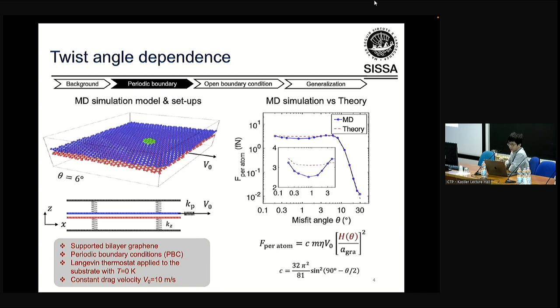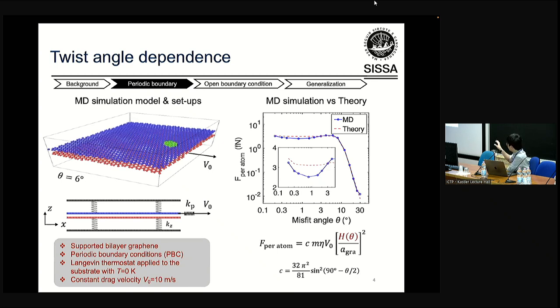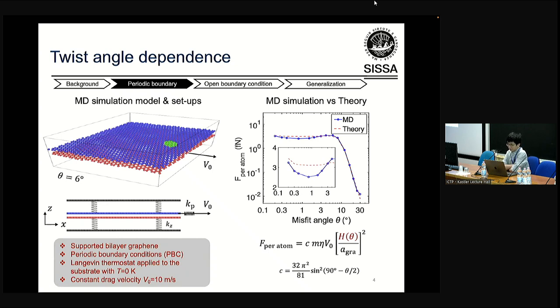Here is the simulation model. We drag the upper layer while the lower layer is stationary, and we highlight the central green region. In the right figure, the blue dots show friction per atom as a function of the twist angle (misfit angle). You can see friction increases as we decrease the twist angle from 30 degrees and saturates at about 10 degrees. We derived some theory for this and it agrees with our MD simulation pretty well.